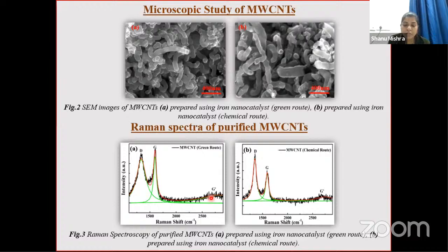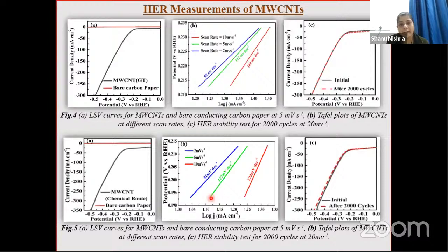After the characterization, to check its electrocatalytic activity, we performed the HER measurement in a 3 electrode cell configuration using 0.5 molar H2SO4 electrolyte, in figure 4 and figure 5. Here figure 4 corresponds to the GT MWCNT, and figure 5 corresponds to the MWCNT by the chemical route. In part A of both figures, we have coated our MWCNT on a conducting carbon paper of 1 cross 1 centimeter square area.